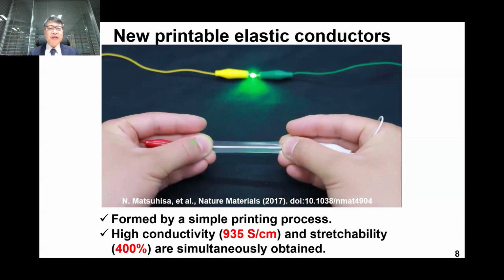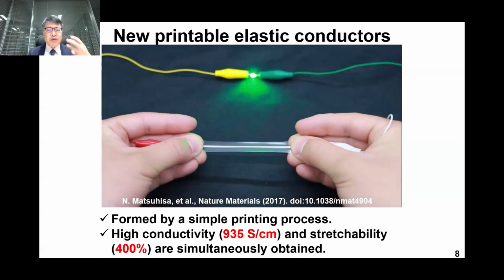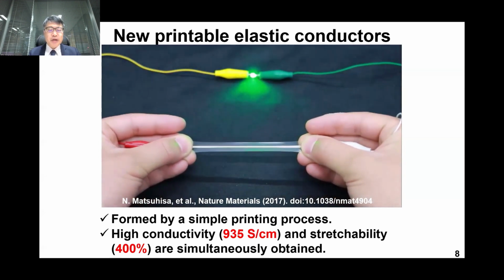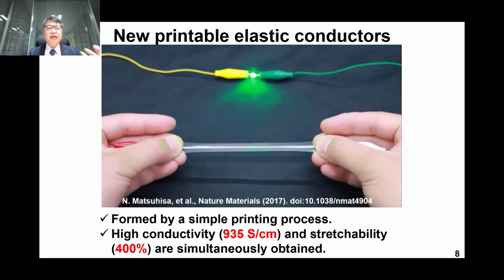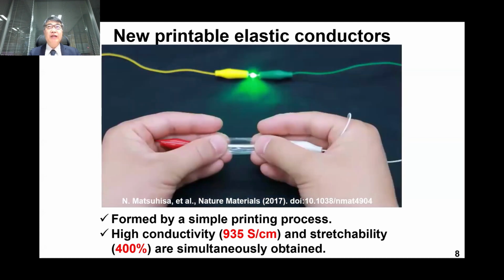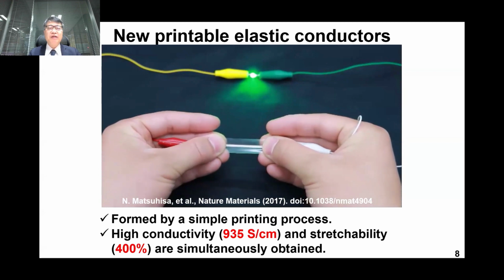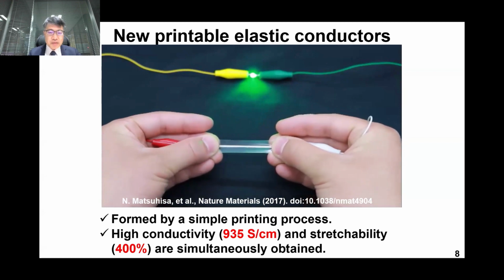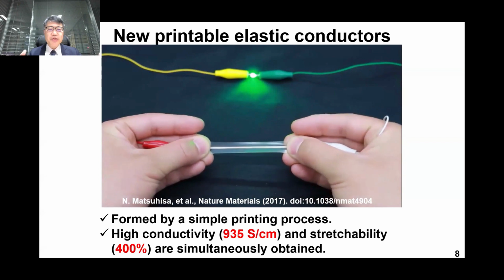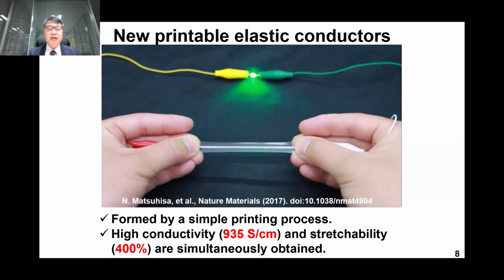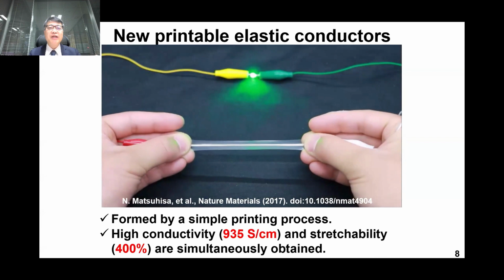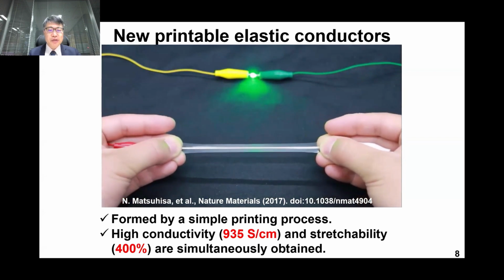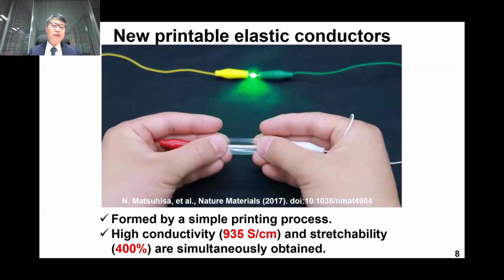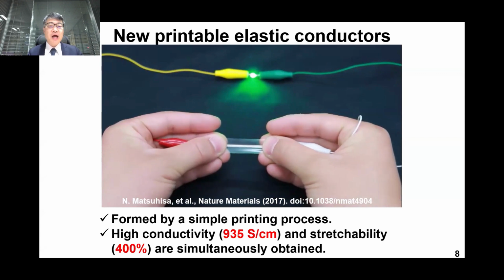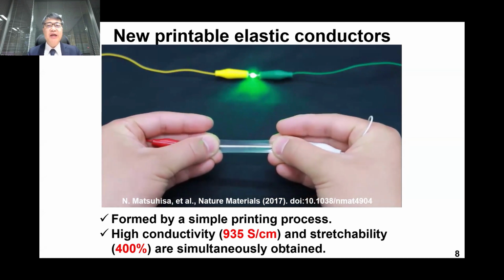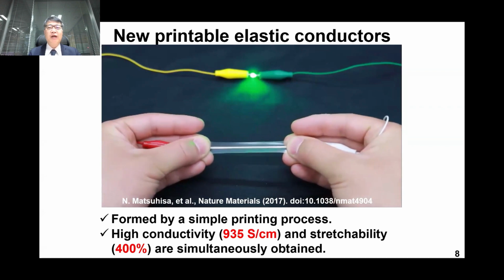And the ink formulation is very straightforward. Silver flake could be mixed together with an organic solvent and a surfactant and the rubbery fluorinated copolymer, and printed onto the rubber substrate by screen printing and annealed at 140 degrees Celsius. Then we can achieve a high conductivity close to 1000 Siemens per centimeter and a high stretchability over 400%.